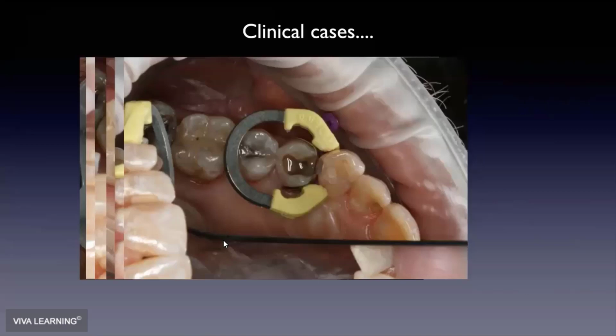Now, if I don't have a bulk fill flowable, I'm never going to make that flowable more than 0.5 millimeter thick. Often it's only 1/4 millimeter thick. However, if I'm using a bulk fill flowable, and in this case it was Extra Base from Voco, then I know those are designed to mitigate the shrinkage, and so I can afford to bulk that up a little bit more. Voco says up to 4 millimeters. I always take that with a grain of salt, and I rarely use it past 3 millimeters.